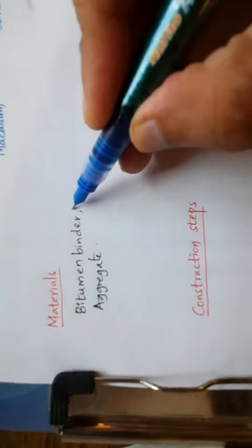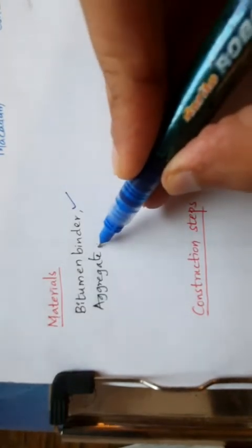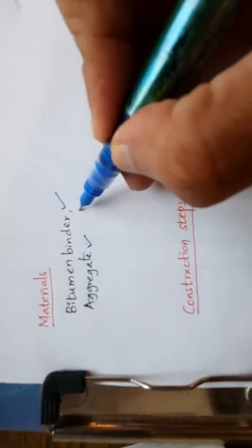For the binder in the pavement, we use VG30, which is recommended for most regions in India. That is what we call the viscosity grade, or we use 60/70 penetration grade bitumen. If it is for a colder region, then we use viscosity grade 20 or 80/100 penetration value as the binder. Then in aggregate, we have already seen the gradation now.